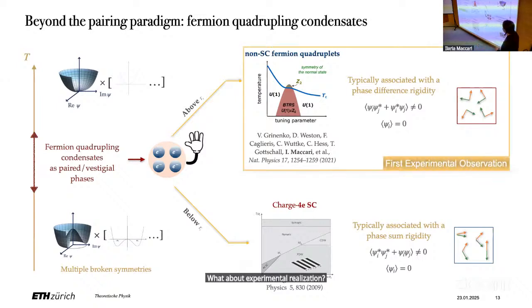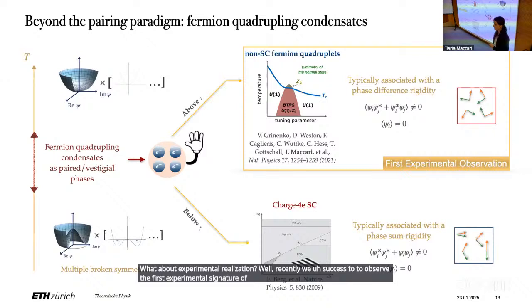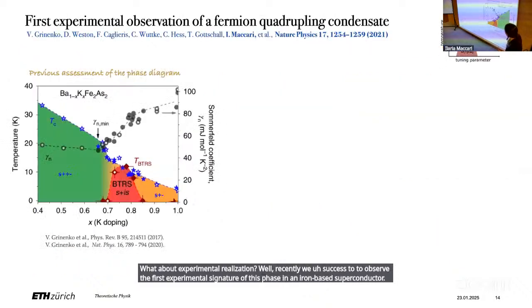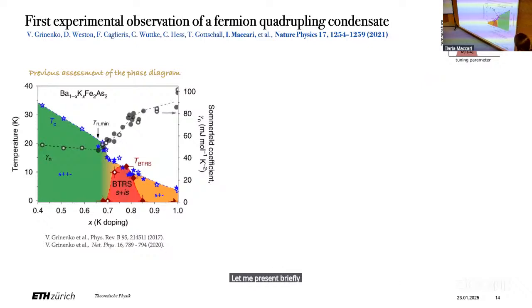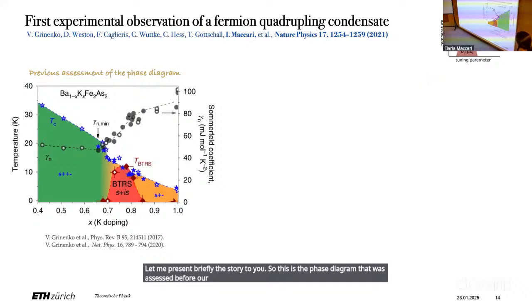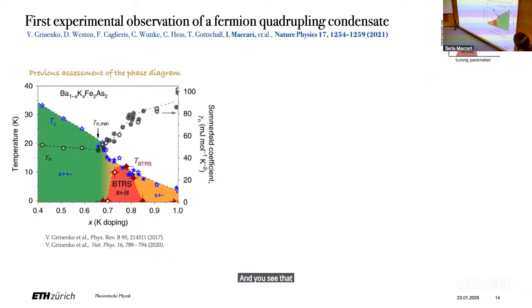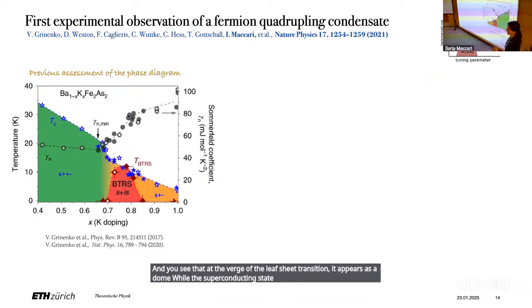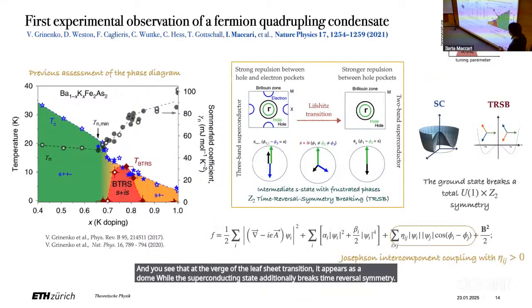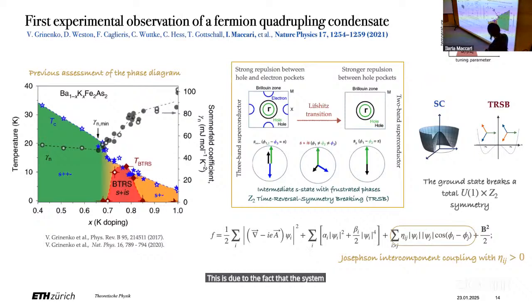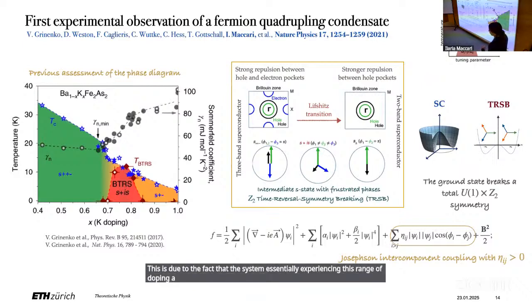Well, recently we succeeded in observing the first experimental signature of this phase in an iron-based superconductor. Let me present briefly the story to you. This is the phase diagram that was assessed before our new experimental result, where here you can see the doping. So this is barium iron arsenide doped with potassium. And you see that at the verge of the Lifshitz transition, there appears a dome where the superconducting state additionally breaks time reversal symmetry. This is due to the fact that the system essentially experiences, in this range of doping, a strong phase frustration between the three bands.